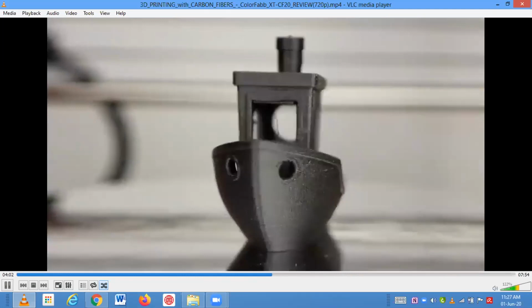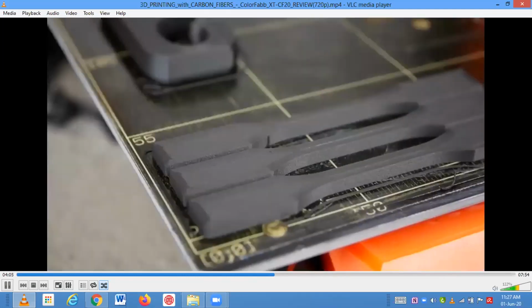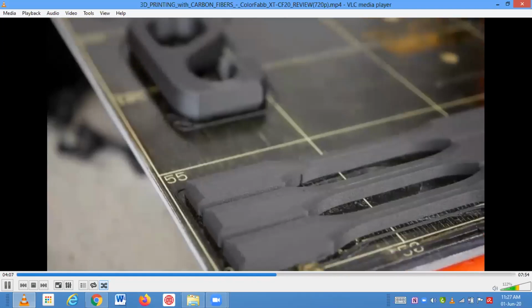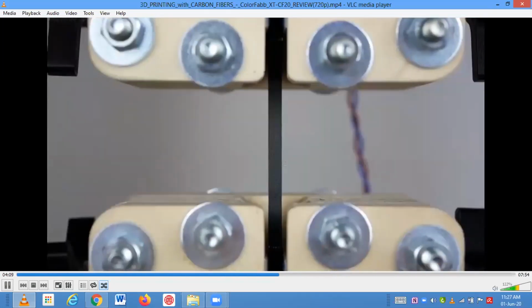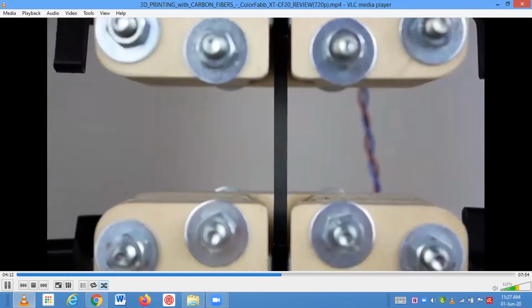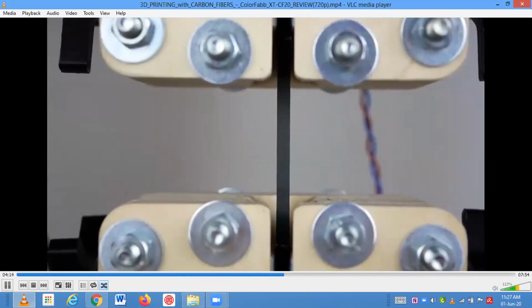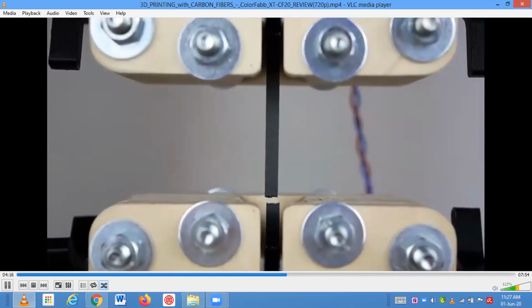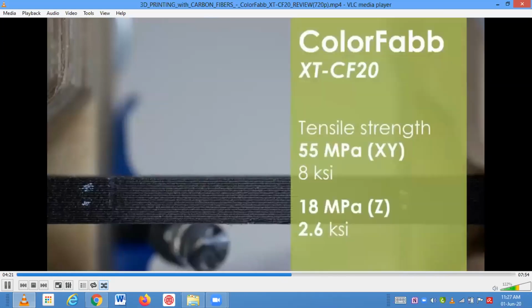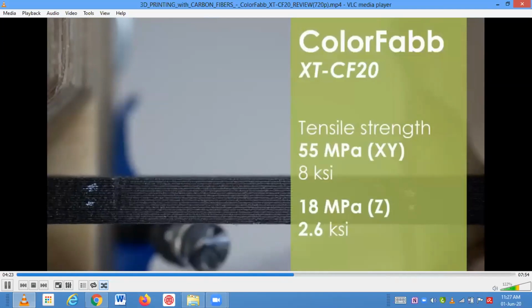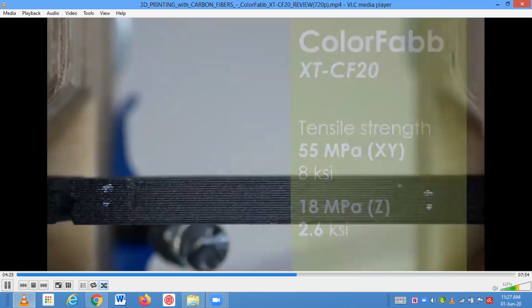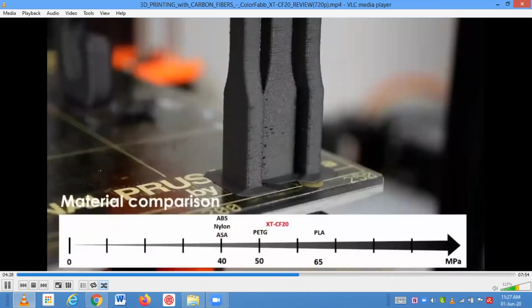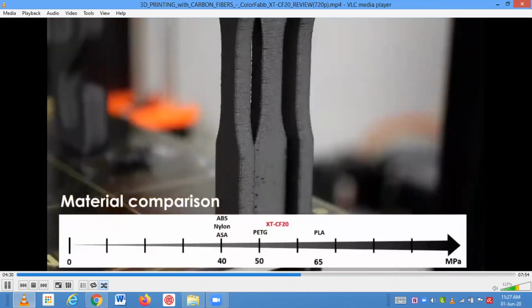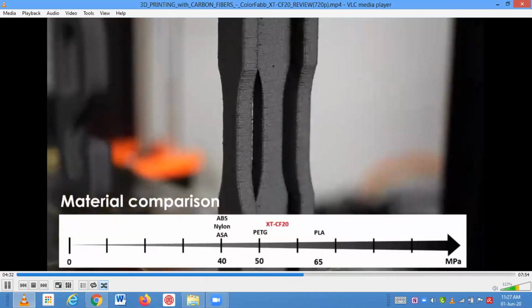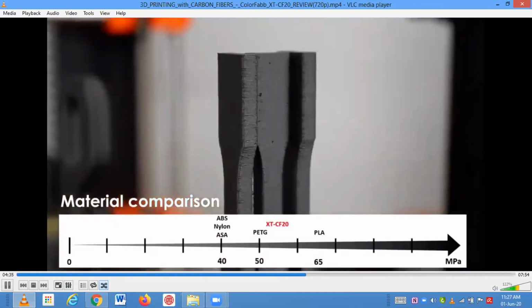Let's now take a look at the material properties of ColorFabb XT-CF20. The tensile strength of around 45 megapascals before drying wasn't very impressive and even lower than regular unfilled PET. After drying the material, it improved more than 20% and ended up with 55 megapascals, which is better but still below regular. Layer adhesion was only okay, and the specimens printed standing failed at 18 megapascals, which is only 1/3 of the strength of the lying ones.